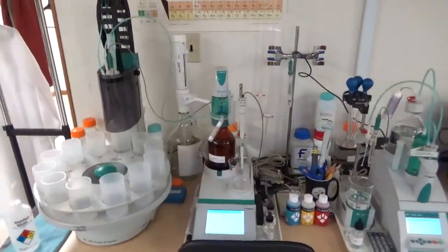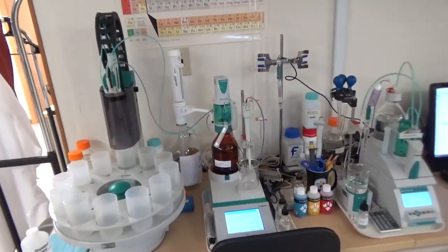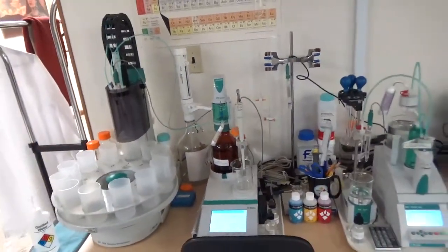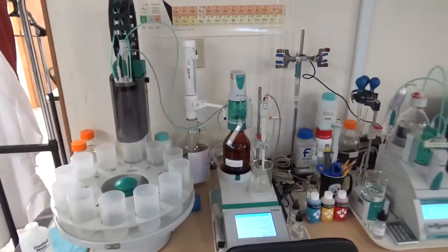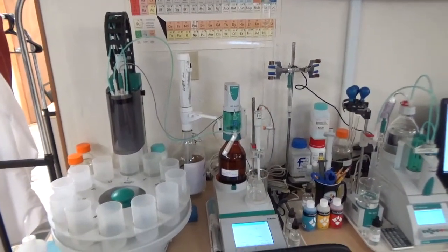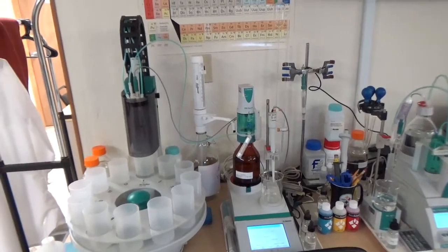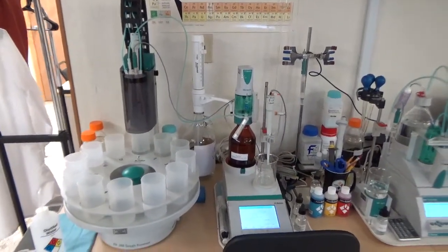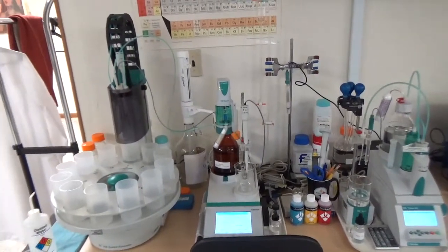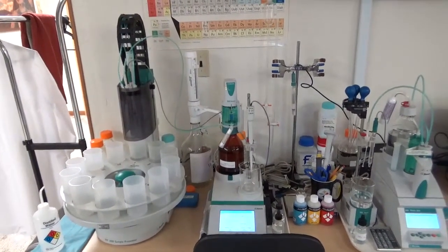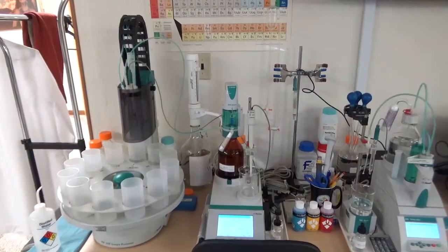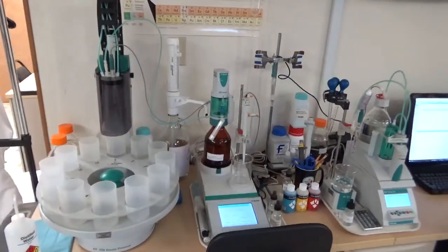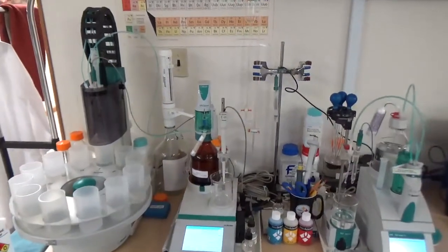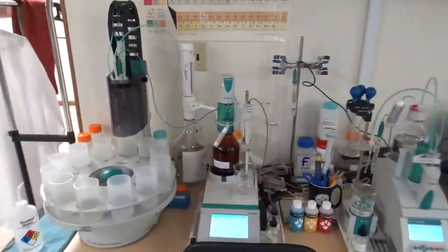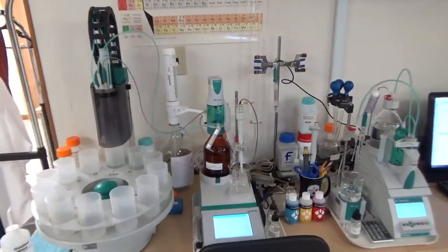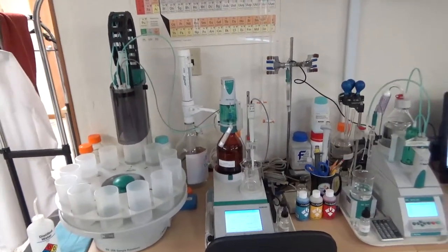CMC has various titration equipment from Metrohm to do different types of titration. The most common is the potentiometric titration to determine chloride content in concrete. We digest a pulverized sample of concrete in nitric acid or deionized water to remove chloride from concrete and get acid-soluble chloride or water-soluble chloride.